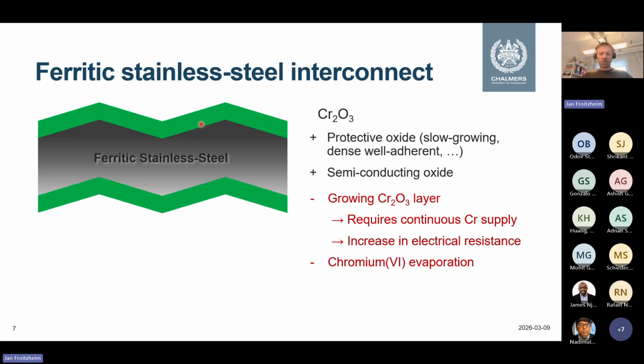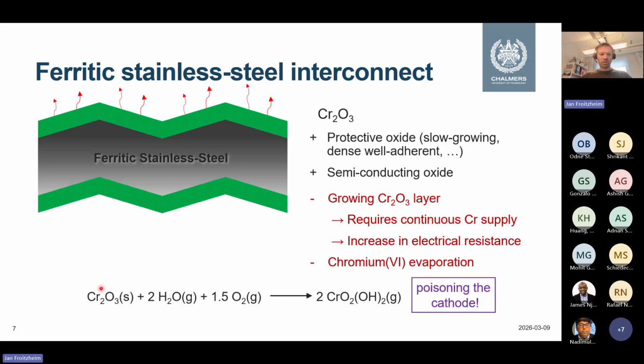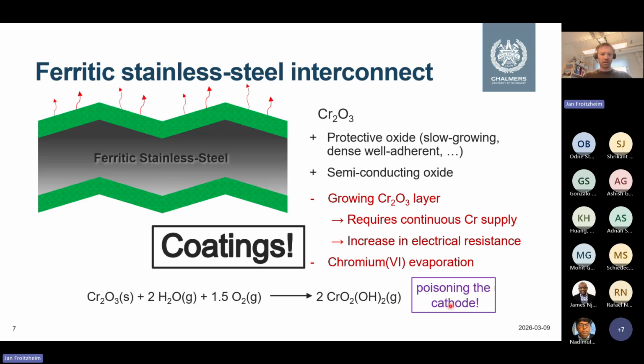Another problem is that we have chromium-6 evaporation. At high temperature, you have this chromia together with water vapor and oxygen forming this chromium oxyhydroxide, which is poisoning the cathode if we're talking fuel cell. So that is a problem, and that's a well-known problem. And the usual remedy against that is use of coatings. I'll come back to that in a minute.